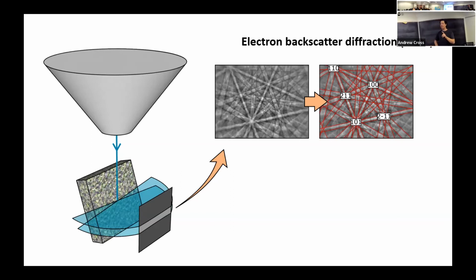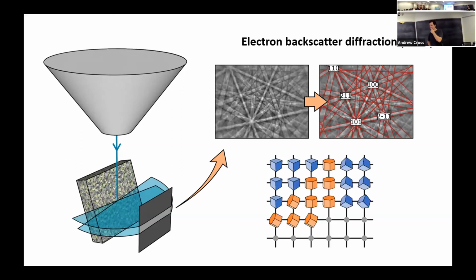And what this means is we're able to resolve crystal structure from the spacing and the angles between the bands that are unique to different minerals and different crystalline materials. We're also able to resolve orientation. So you might see a rotation of the pattern that corresponds to rotation of the crystal lattice. So we raster the electron beam across the sample in a grid. At each analysis spot, we get a crystal structure. So we've got a blue cubic phase and an orange hexagonal phase here. And we're also able to resolve changes in orientation.